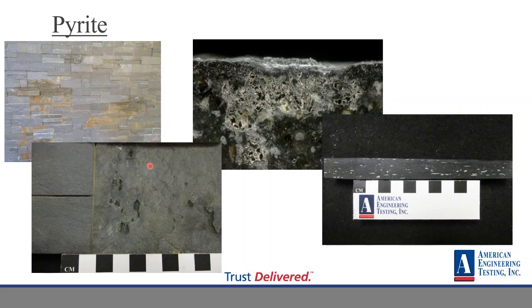So we got it, took some photos. You can see the one below it here, where the laser pointer is, started to get this really nasty pitting from the weathering of pyrite. Up here, this is a cross-section view where you can see a honeycomb texture of pyrite when it's starting to react and cause nasty things to happen to those really nice veneers.